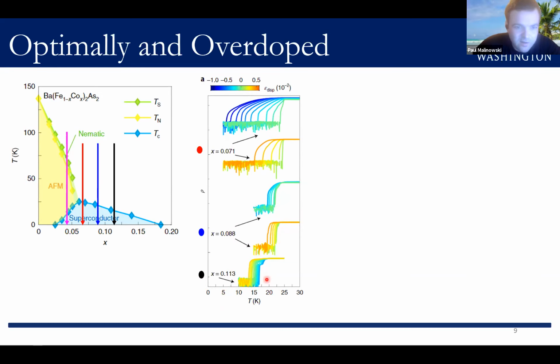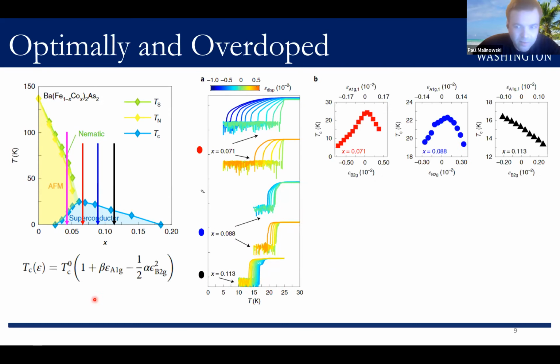And then for the more overdoped 11.3% sample, it's even less sensitive and no longer symmetric for positive and negative strain. So we can understand this evolution a bit better through some basic symmetry considerations. When we apply uniaxial stress along the 110 direction, we don't just induce the anisotropic B2g strain, but we also induce some amounts of symmetry conserving A1g type strains.